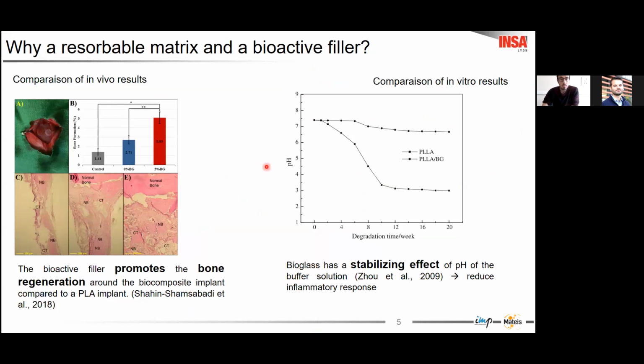Here I will present some examples from the literature. First, we have an example of an in vivo study showing that the use of bioactive filler increases the rate of bone formation. Here we see the use of 5% bioglass, which promotes bone regeneration around the implant. On the other side, we have an in vitro study showing that bioglass can stabilize the pH of the solution. This effect could reduce a possible inflammatory response already observed during implantation of these systems.